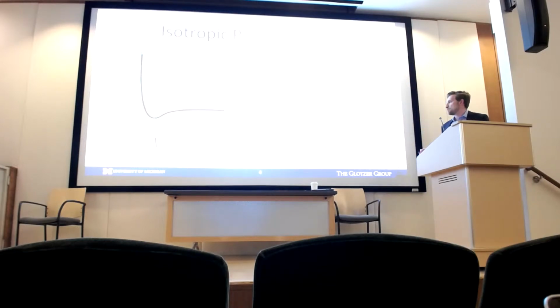So this is a very accurate model for the interaction of noble gases, for example. And you can tune this potential by changing these parameters here, sigma, which is some arbitrary length scale, and epsilon, which is some arbitrary energy scale. And you could also change the slope of these repulsive and attractive ends here. However, then it technically wouldn't be a Lennard-Jones potential anymore. And it actually makes a lot of difference how steep this potential here is. That's something that my coworker Alan showed in his work.